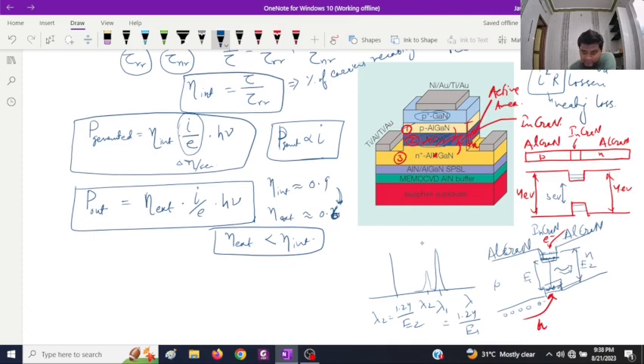So in this way you can see a very high dominant line at lambda 1 corresponding to this energy level. Unlike earlier, when normal LEDs had a very broad spontaneous emission with a line width of around 80 nanometer, here this line will be of the order of 1 nanometer or even less than 1 nanometer.